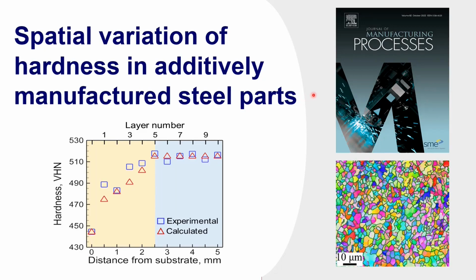Grade 91 ferritic steel containing 9% chromium, 1% molybdenum, and 0.1% carbon is widely used because of its good strength, creep resistance, and radiation tolerance. During additive manufacturing of this steel, martensite forms because of rapid cooling, and the extent of tempering of martensite significantly affects the mechanical properties of parts. Currently, there is a lack of quantitative understanding of the tempering kinetics and the resulting hardness variations.